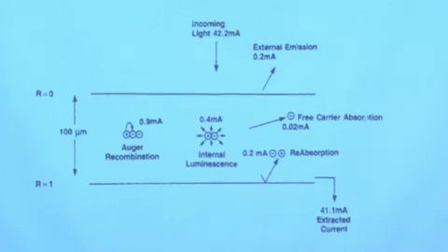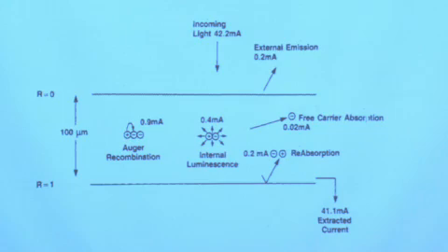It emits a photon inside of your solar cell device, and that photon bounces around a few more times until it's reabsorbed, generating another electron hole pair. And that is essentially the major boost in some of these ultra-thin, high-performance solar cell materials, such as the Alta devices, a record efficiency 28% gallium arsenide cell, is the ability to do this photon recycling.